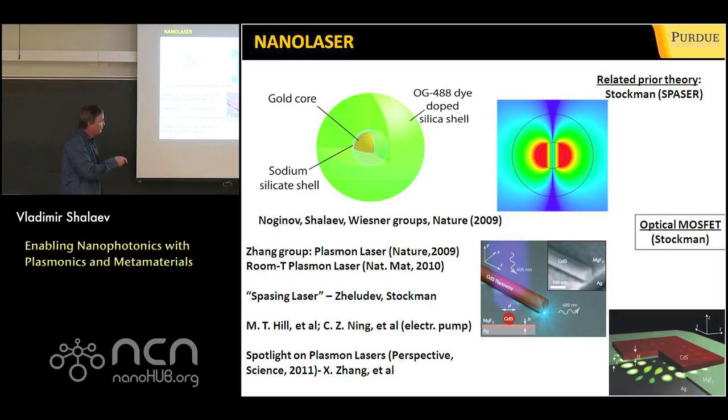It was largely concentrated between this semiconductor rod and the metallic film, and when it propagates, it gets amplified by this optically pumped cadmium sulfide nanowire. That nanolaser worked at relatively low temperature. Then they generalized it and used this kind of plate, and that enabled room temperature nanoscale lasing.